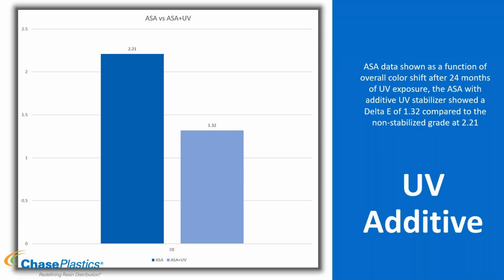Delta E, delta meaning change, is the change of overall color shift in a material. When they measure color, they typically use the LAB scale - lightness, yellow-blue, and red-green. They take the values to begin with, then after aging, and read it again. In this study, they exposed it to 24 months of UV, then compared the lightness, yellow-blue, and red-green to give an overall score of color shift.